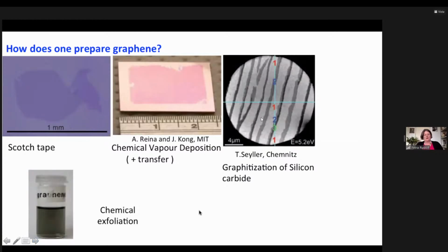You probably all know that there are very different ways to make graphene. Scotch tape was the method used by Novoselov and also by many of the people who investigated the exciting transport properties, but that is of course not a method that you can scale up. So people found other ways to make it, for example, from silicon carbide. Now silicon carbide is very expensive, so you have to have a good reason for using it, but you can get very nice graphene on top of that. Most people work with chemical vapor deposition and transfer, or with chemical exfoliation. And I shall show you some results of both methods.